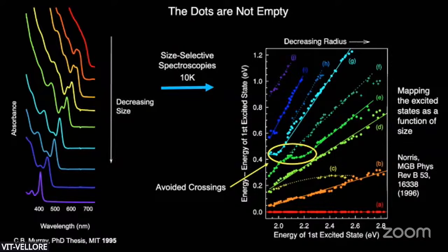So you're going from a process where the box appears to be empty from the electron's perspective, to the electron beginning to see that, wow, there's a lot of atoms in there, and I'm scattering off these atoms in a way that is now what we call coherent. That is a property of the bulk material. So that tells you where this property begins to go from the atomic to the bulk. There are so many properties of materials you can study this way, and every one of them starts to see the bulk properties at different rates.